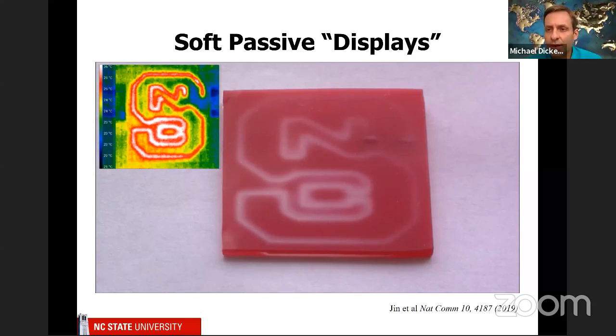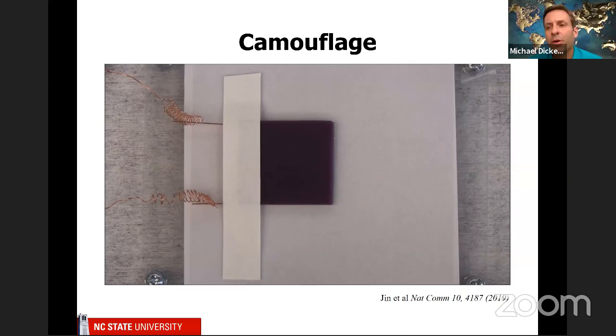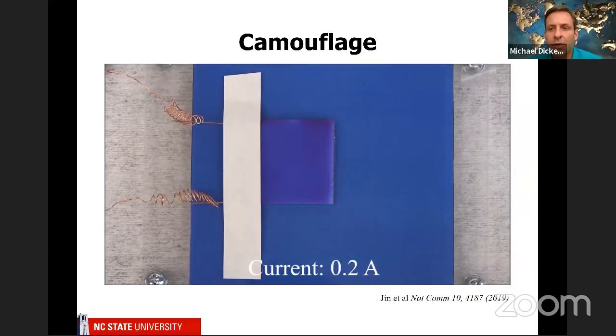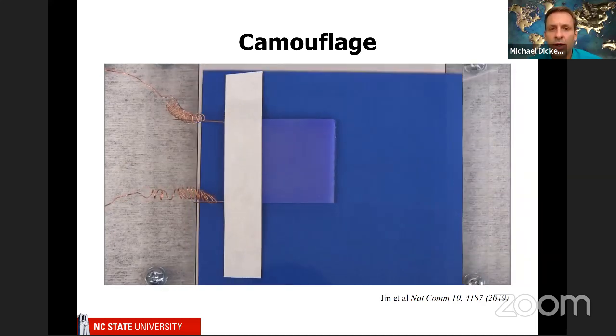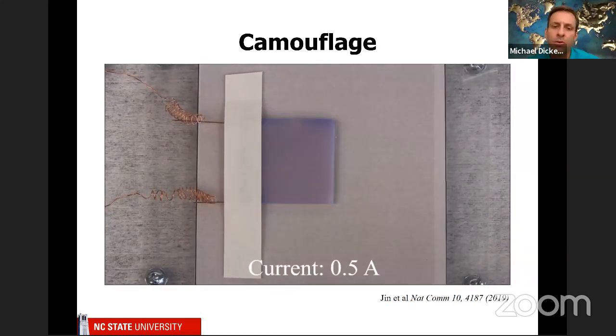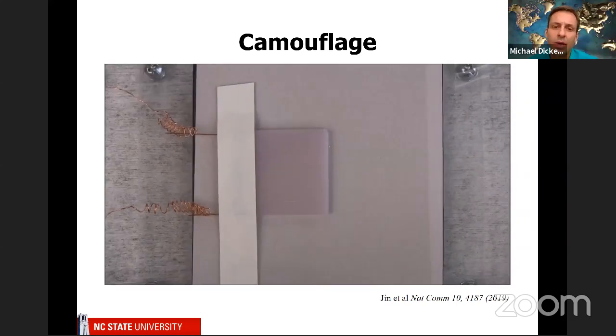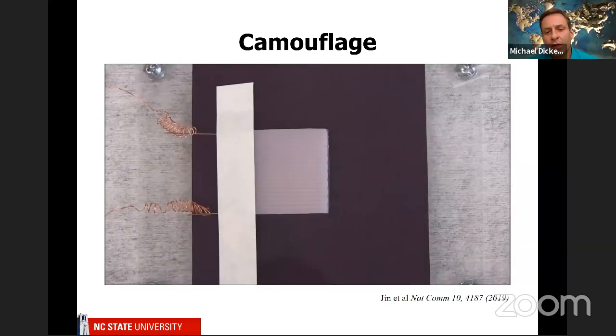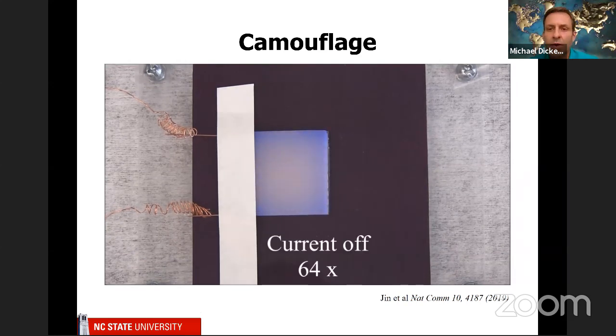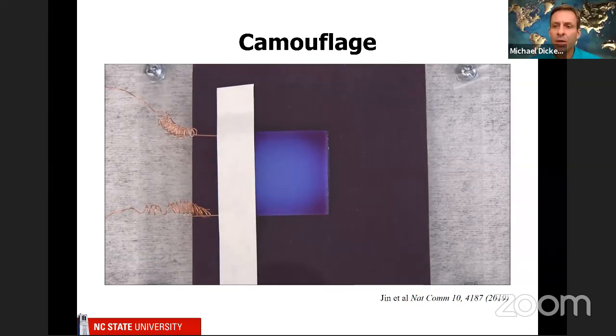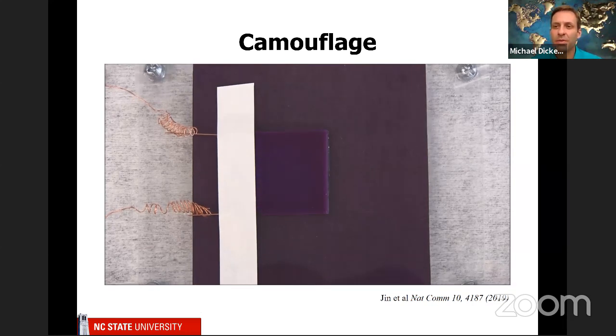And another step with this is you can take, let's just say, red and blue pigments, which trigger at different temperatures, and mix them together to get purple. Now, if you run a little bit of current through it, you can make the red disappear. So now it appears blue. And then if you run more current through, you can make the blue disappear because now it's at a warmer temperature and it looks white. And then you just wait. Unfortunately, it's slow because it's a thermal process, but you have to wait for it to cool back down and it will go back to its original color and condition. Okay, again, I would say beautiful, but not surprising.